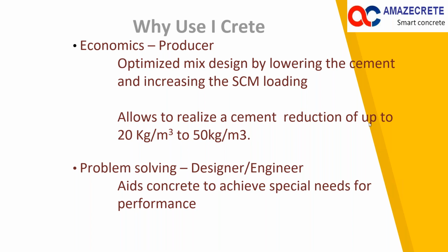For example, if we have OPC mixes, let us say a mix of OPC 400 kgs or 450 kgs at a particular dosage like 1.5 or 1.8 or 2%, we can reduce about 50 to 55 kgs per cubic meter. And on the lower end of the dosage, if we have 0.8 or 0.7% dosage, we can reduce about 20 kgs per cubic meter. So the range is between 20 to 50 kgs, directly from OPC to OPC we can reduce.